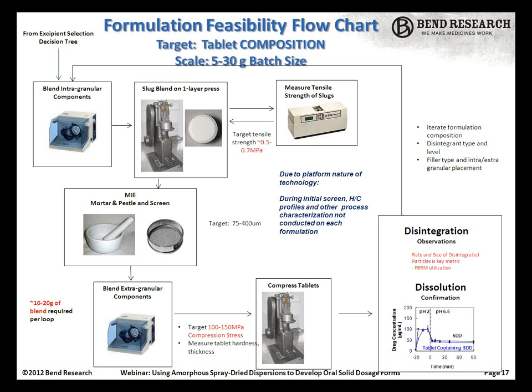So we will generally slug on a single layer tablet press. We will mill these manually, either with a mortar and pestle, or sometimes use a small co-mill cone screen. At this point, again, I mentioned it's not very critical on particle size. We found the granule particle size is not critical to dissolution, so we don't do a whole lot in the screening mode here. We'll blend with extragranular in some cases, and then compress tablets, usually on a single layer press at this stage. So again, this is very minimal, maybe 5 to 30 gram batch sizes for these tablets. And we'll be looking at disintegration and dissolution as the metric here, in the dissolution test that Chris showed.